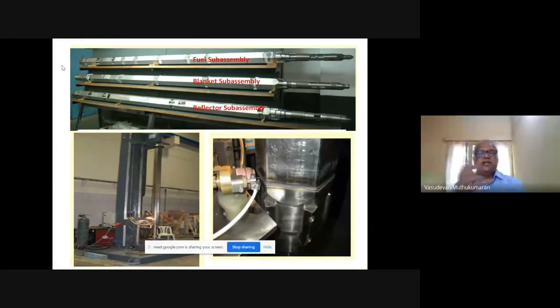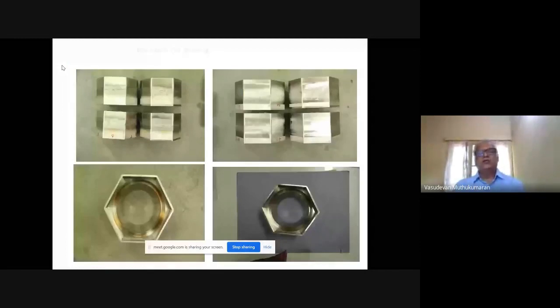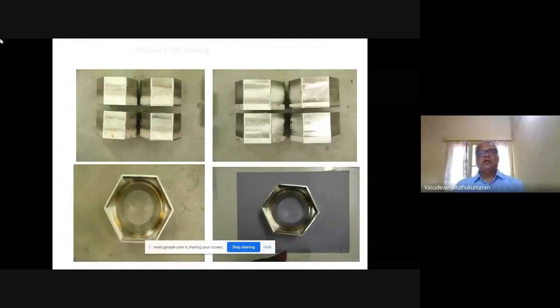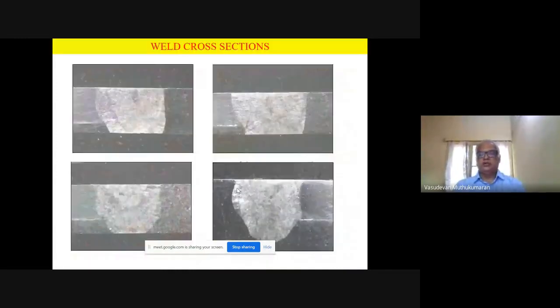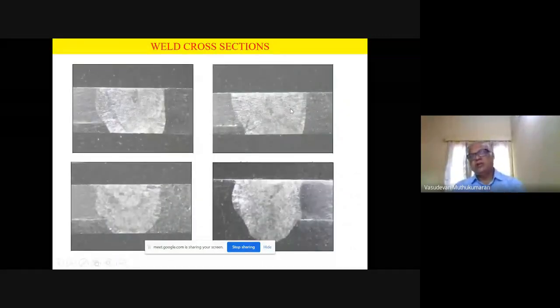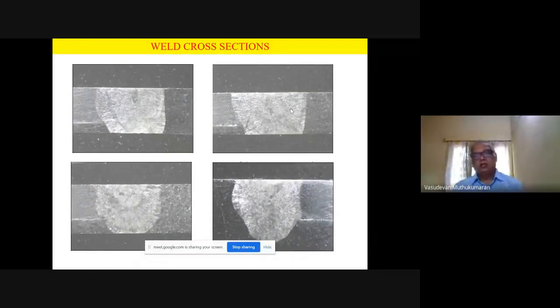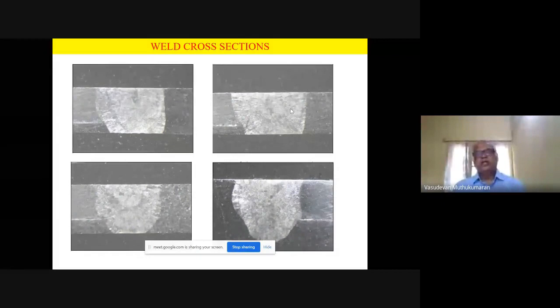So we again suggested ATIG welding. On the mock-up samples we have done, we could do the same thing in a single pass, and we were successful in reducing the heat input and distortion again. It also passed all the quality checks. You can see full penetration achieved in a single pass here. You can see single pass ATIG welding. So the ATIG welding technology we developed in the lab is now transferred to industry. Our central workshop is using it for welding various components, pipes, PFBR fuel subassemblies, and various plates, successfully. The automation of the process really helped in achieving our requirements.